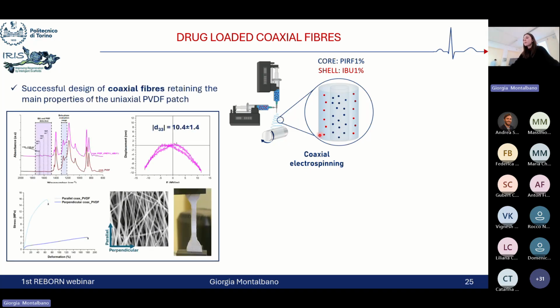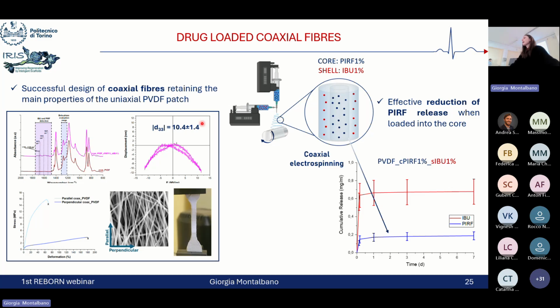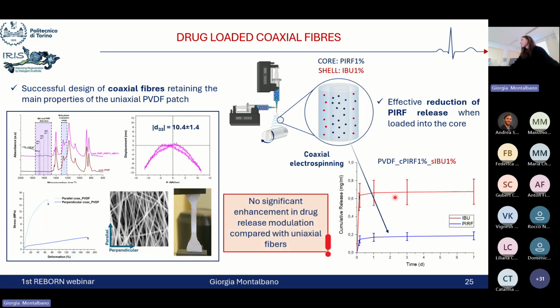So here, the optimized process led to the successful design of coaxial fibers that could retain the main properties of the uniaxial PVDF patch previously described. And also, as you can see here from the release test performed with the drug, the internalization of pirfenidone into the core of the coaxial fibers could induce a reduction of its release compared to ibuprofen. However, no significant enhancement in the release modulation was verified compared with the uniaxial fiber.